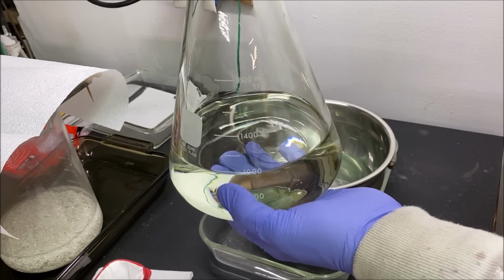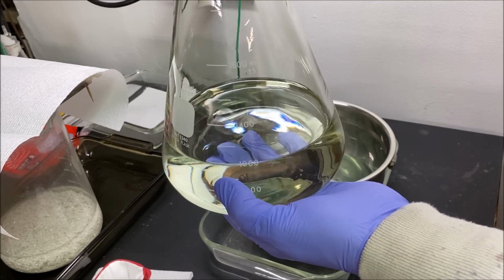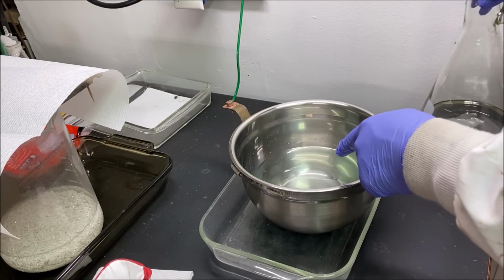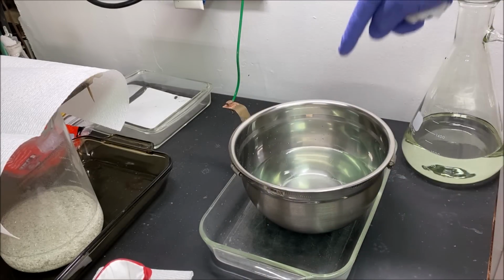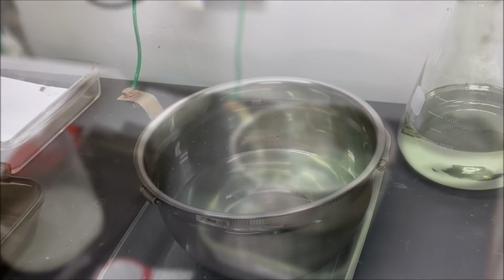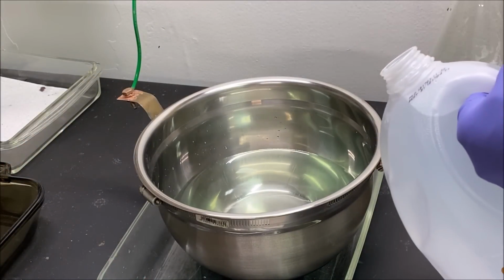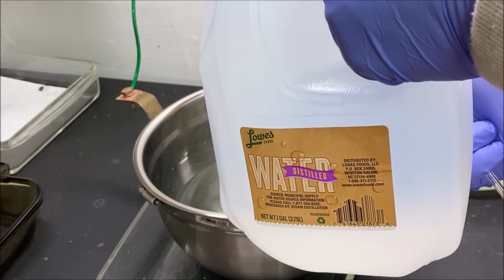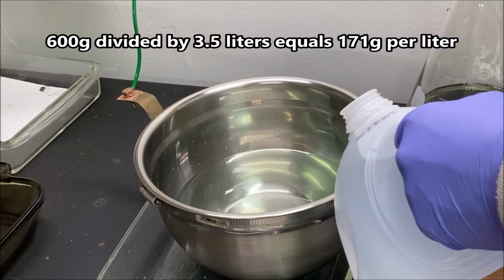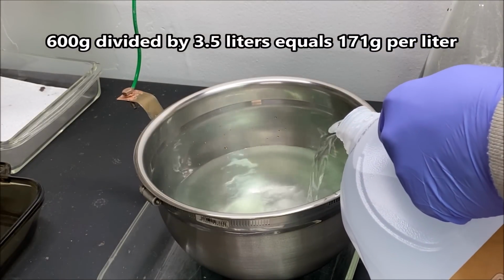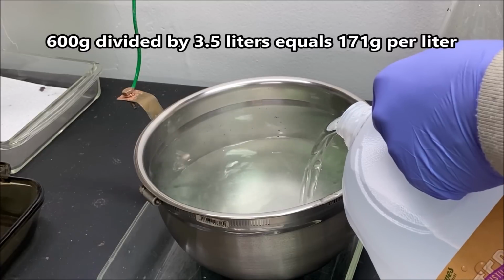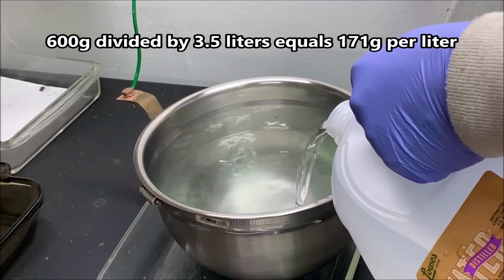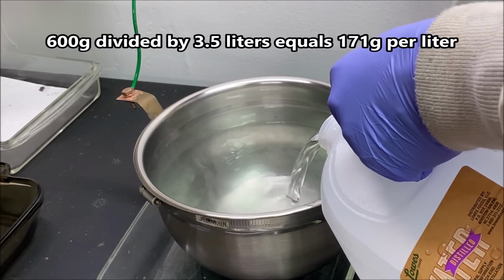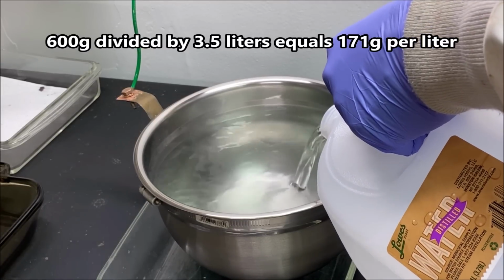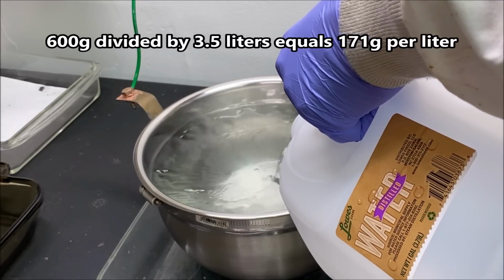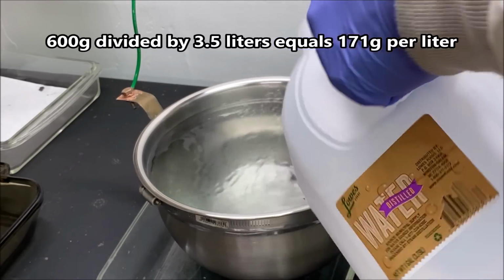So there's about roughly 600 grams of silver in this solution in this bottle, and 600 grams of silver dissolved in that solution in the silver cell. Now I'm going to take some distilled water and top this up to about 3.5 liters of liquid. We're diluting the silver nitrate solution so that we're creating an electrolyte that contains about 171 grams of pure silver dissolved in a liter of liquid.